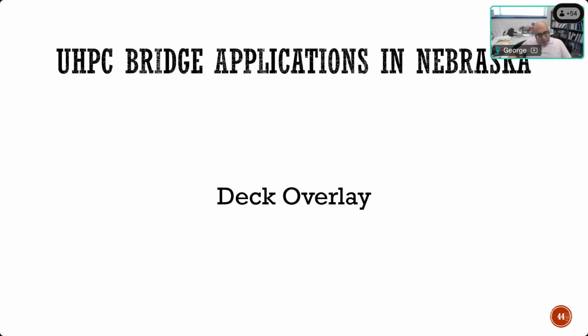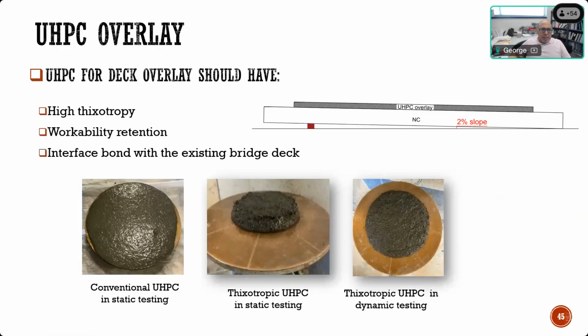So one of the last applications is deck overlay. And I would like to mention that when you use UHPC in deck overlay, we need to look at a different type of UHPC, not the same one we use for structural components or for repair. The reason is that when you add a thin layer of UHPC on top of a deck with slope, you don't want it to be basically moving and changing the thickness from one place to the other. You want it to be stable, and you cannot top form it.